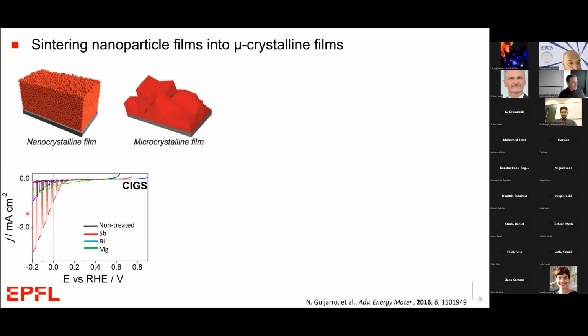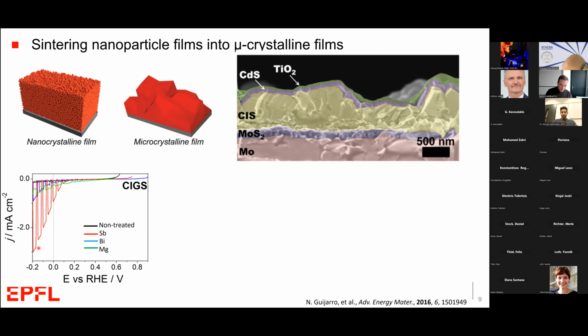For a photocathode for hydrogen production, we want a large negative current density. And so when the light is on, we have the current here. And then when the light is turned off, it goes back to zero. That's also showing us that we have this photocurrent effect. So we can see a big difference when we use this antimony treatment versus the black curve, which is non-treated, which has essentially no photocurrent. We can already see the effect of this grain growth in these systems.